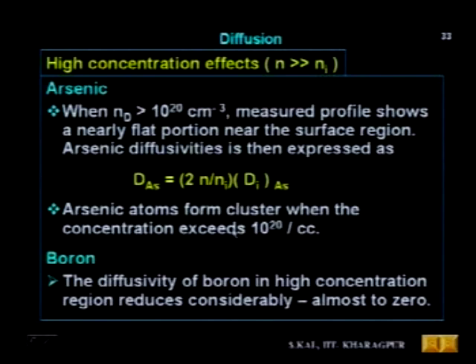In case of boron, it has been observed that the diffusivity of boron in a high concentration region reduces considerably, almost to zero. If the boron concentration is more than 10 to the power 20, in the range of 10 to the power 21 or something like that, then it has been observed that boron diffusivity reduces considerably, and sometimes it may reach almost near to zero. So those are the high concentration effects of arsenic and boron. Now we will discuss high concentration effect of phosphorus.